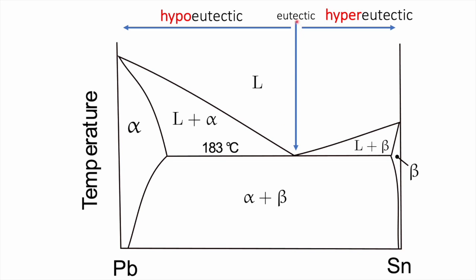Of course, you can have compositions across the range, and alloys in this domain are known as hypo-eutectic, and in this domain as hyper-eutectic. So if I have an alloy of this composition, as I cool the liquid, I will first get the precipitation of beta. When I get the precipitation of beta, which is poor in lead, the liquid will become richer and richer in lead, and its composition moves down this phase boundary, while the composition of the beta moves down this phase boundary. And eventually, the remaining liquid will decompose into a mixture of alpha and beta.